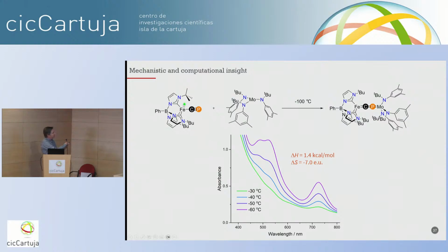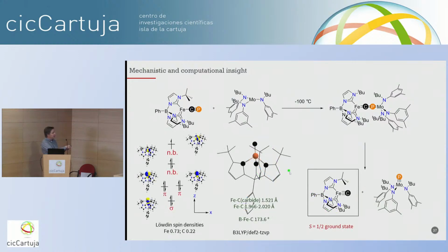So if you look at this reaction very carefully, at low temperature, you can measure a reversible equilibrium between the reagents, and what we propose is this compound here. And from the resulting thermodynamic parameters at minus 100 degrees Celsius, the equilibrium constant here is about 1. Again, this shows how non-nucleophilic this phosphorus atom is. But then as we warm it up, then there's enough thermal energy to drive the cleavage reaction to make the phosphide, and then this must leave behind a carbide. From DFT, we show the lowest energy spin state is spin 1/2, much like an iron nitride we made. And so the computed geometry is slightly bent at the iron because of the fact that it's Jahn-Teller active.